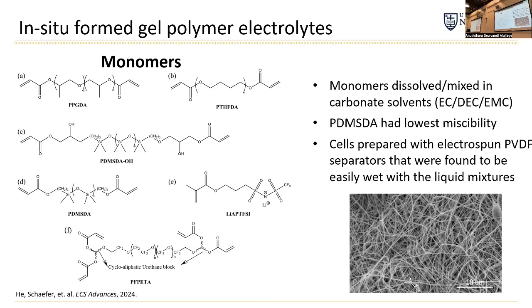The reason why we looked at these, along with the poly-THF, is that in all cases, they have a lower oxygen density than PEG, and so we thought they should give higher ion conductivity. And we looked at cases where we used this ionic monomer here. So instead of a conventional salt, we use this salt, which again has a polymerizable handle on it. So we could try to polymerize the anion into the polymer network, to reduce the motion of the anion and get higher cation transference.